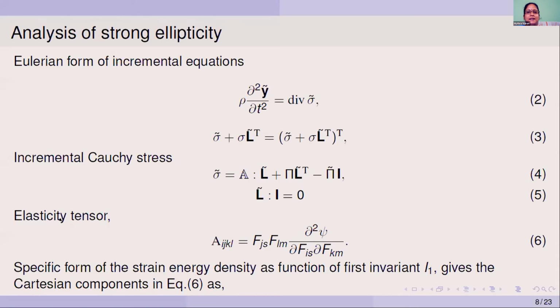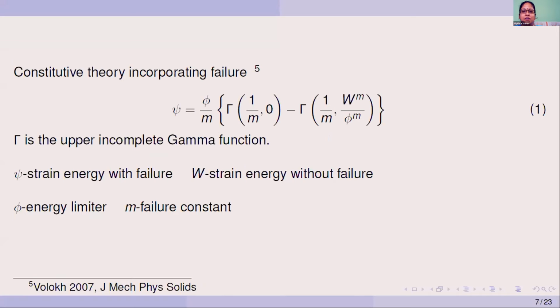And the elasticity tensor A in its component form is given by this equation as shown here. This F is the deformation gradient from the undeformed configuration of the body to the deformed configuration. This psi is the strain energy density function incorporating failure, which is as given by equation 1.